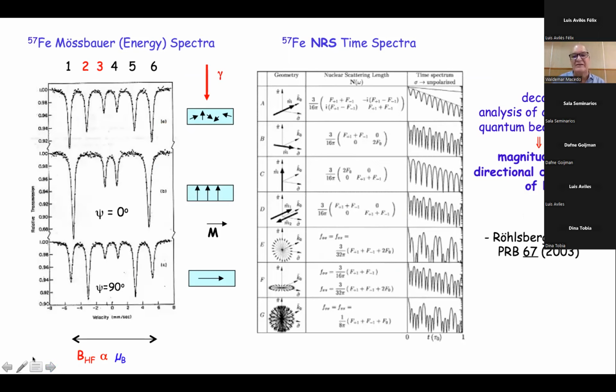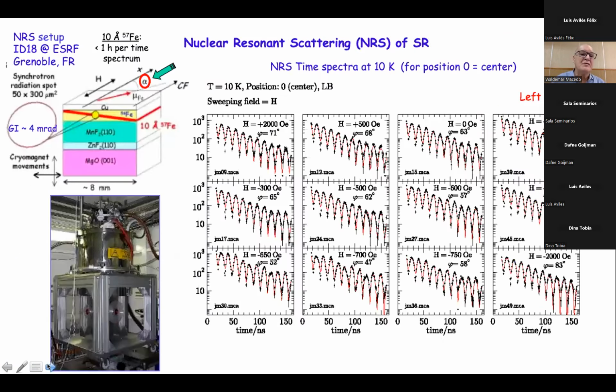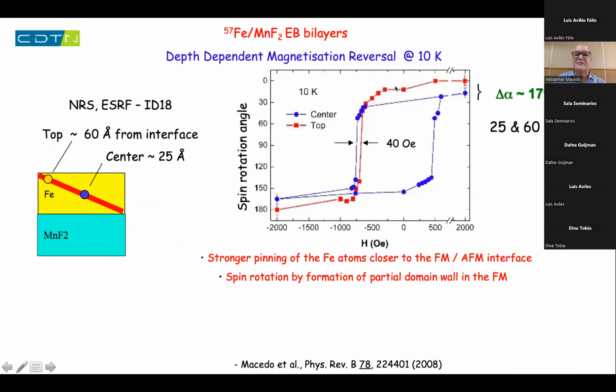Okay, it's equivalent to the normal Mössbauer spectra. By using the small size of the synchrotron beam, we could move the sample in front of the beam, doing measurements along all the hysteresis loops of the system, and then we were able to see that the magnetization reversal is dependent on the depth. That means the pinning of the iron is much stronger closer to the interface when you compare it to another point that is further away from the interface, at the center of the sample.